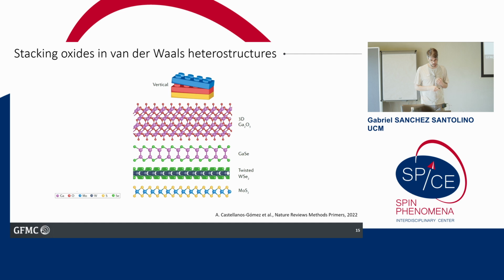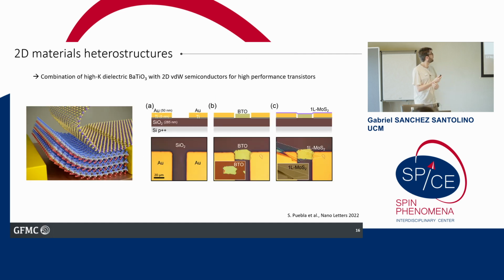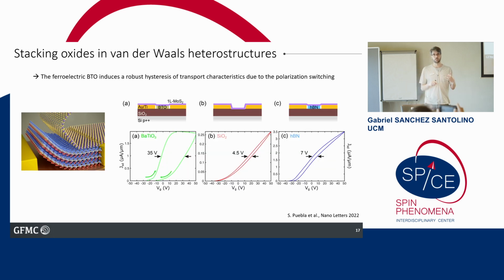For example, one of the first things we did with it was making high-performance transistors, mixing it with conventional 2D semiconductors. We can just transfer our barium titanate layer, which is a very high dielectric constant material, and put one monolayer of molybdenum disulfide on top, and we have a transistor. Because of the strong polarization of the barium titanate layer, we get this kind of characteristics in the transport measurement, where we have a very big hysteresis due to the polarization switching up and down in the transistor. So we can now use these kinds of materials to design new devices.